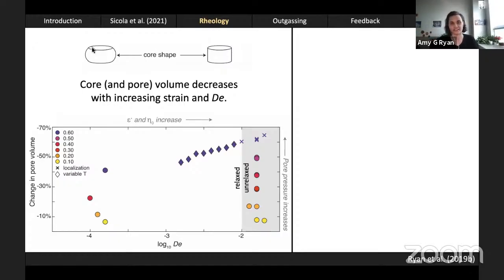And I should say that the upper and lower diameter of these cores doesn't change significantly from the initial diameter of the core before deformation. Now I did a little bit of trickery here, and I calculated the core volume based on the core shape, and then I used that to try to understand what a pore in the core might be experiencing. So in that way, I can estimate the change in pore volume as a result of strain, which makes sense that it decreases as strain increases, and with increasing Deborah number.